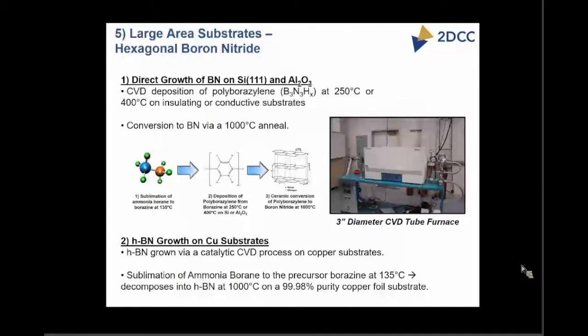And then another similar type of application in terms of large area substrates is hexagonal boron nitride. This capability exists in 2 forms. One, direct growth using ammonia borane as a single source precursor. It decomposes, and you can do this at fairly low temperatures on various substrates and then do a high temperature ceramic conversion. The advantage of this is it gives you a very low roughness substrate for deposition of other types of 2D materials.